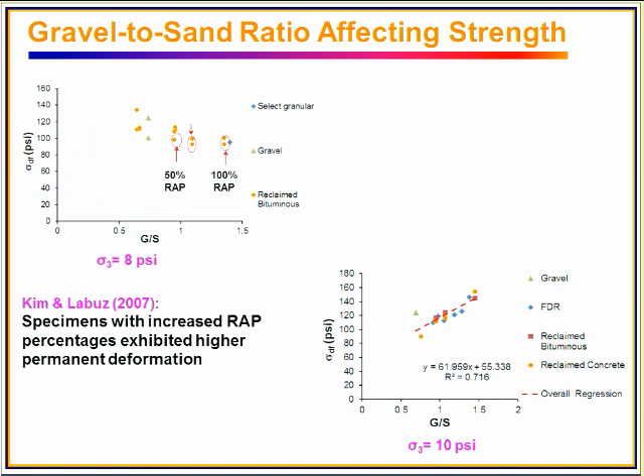So the trend is kind of obvious for the bottom figure, but for the upper figure it's not that obvious, because it involves some recycled materials. According to a report completed for MnDOT, specimens with increased RAP content exhibited higher permanent deformation. As you can see, 50% RAP and 100% RAP show pretty much the same peak deviator stress at failure. But actually, according to the Kim and Labuz study, there should be some difference in their